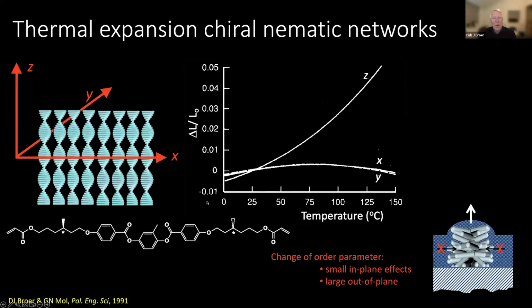Now, going back to the chiral materials again, then you see actually similar effects. You make a film with the chirality such that the helices of the molecules are perpendicular to the substrate. And if you then measure the thermal expansion coefficient, it is about zero in the plane of the film, because the two polymer orientation directions are just balancing, canceling each other out. And you have a very high thermal expansion in the Z direction along the helix axis.